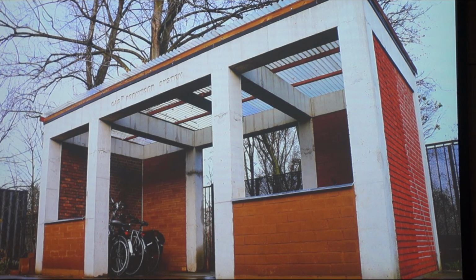And just to give you an idea of what has happened after 2 years, on this side, which is the block without cow-dung, on the back side of the building you can see the erosion, which is almost 3 to 5 centimeters, whereas the one with cow-dung has no erosion. And this is outside and it's exposed to the rain, and it rains quite a lot in the Netherlands. And there's no measurable erosion. You can visually see some sort of erosion, but there's no measurable erosion in this case. So it's really doing well, and it's an example that these structures can survive in most climates as long as you design them well.